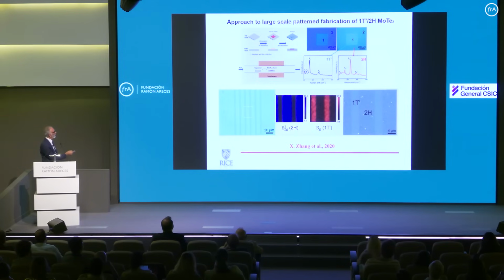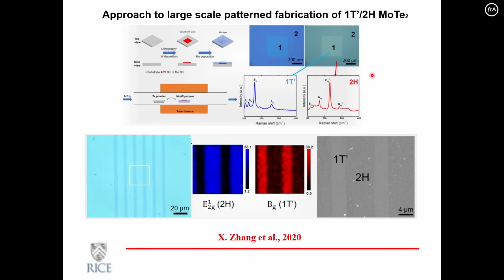And this is, again, a very different type of structure. It's made of what is called molybdenum telluride, very similar to those molybdenum sulfides that I showed you. But here, the difference is that molybdenum telluride has two different phases. So the same composition can exist as a metallic phase and a semiconducting phase.